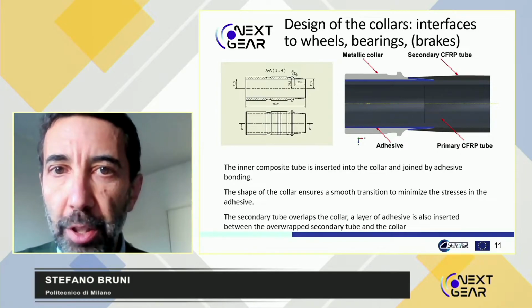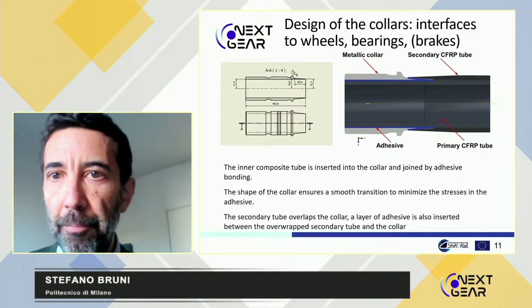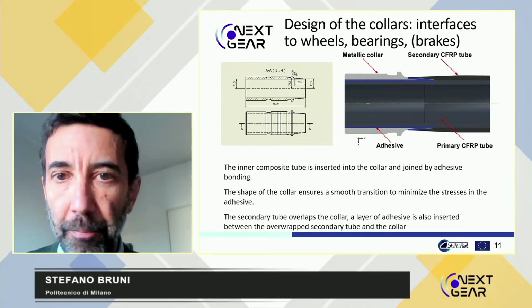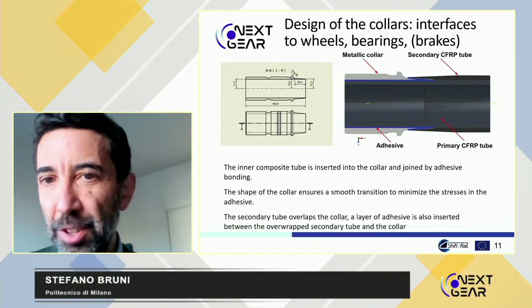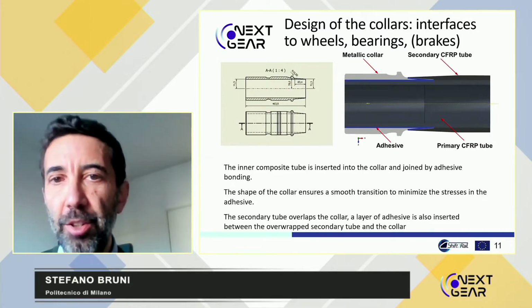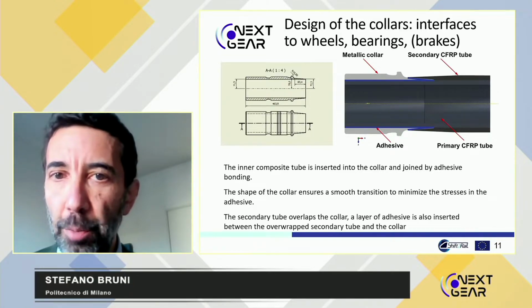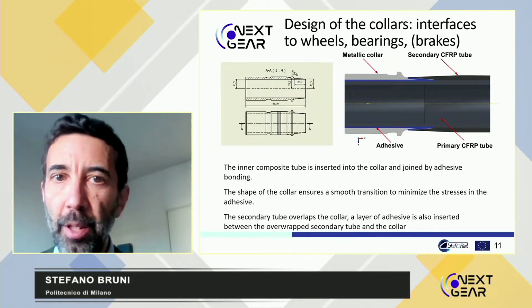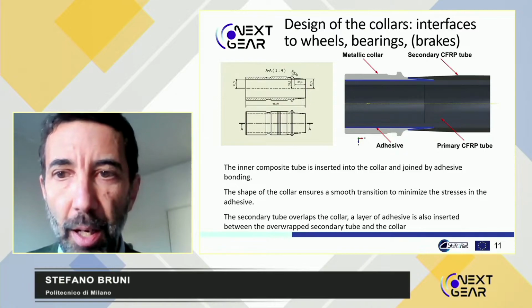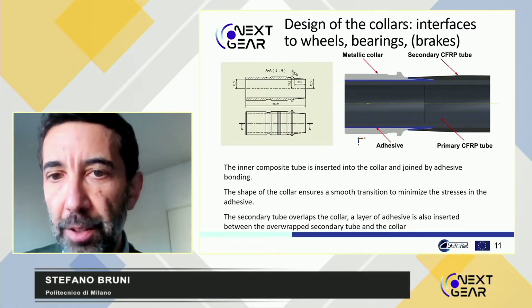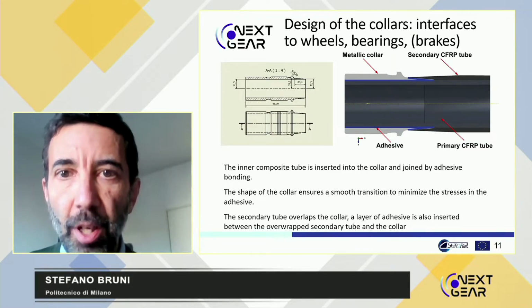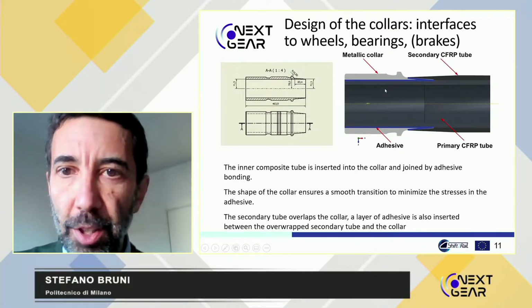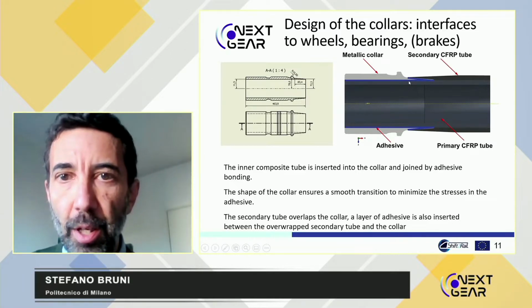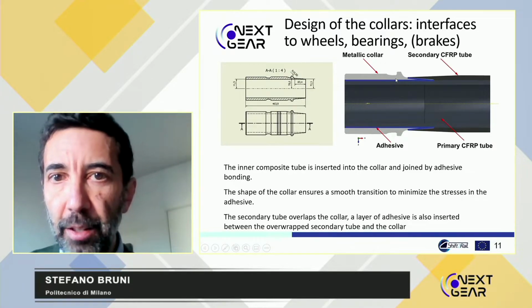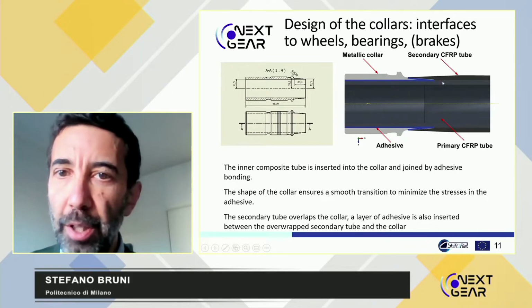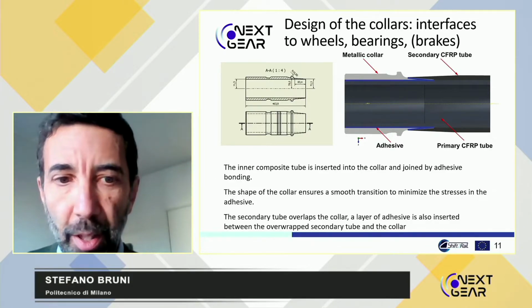In terms of the joining of the metallic collars to the primary and secondary tube, this was another very important and time-consuming part of our work because this is totally new, and of course we wanted to design a solution which is completely compatible with the stresses that need to be exchanged between the metallic and non-metallic parts in the axle. So this was done by means of finite element models and finite element analysis. We found that it is particularly critical to ensure a smooth transition where the metallic collar transitions into the part of the axle which is only made of composite material.